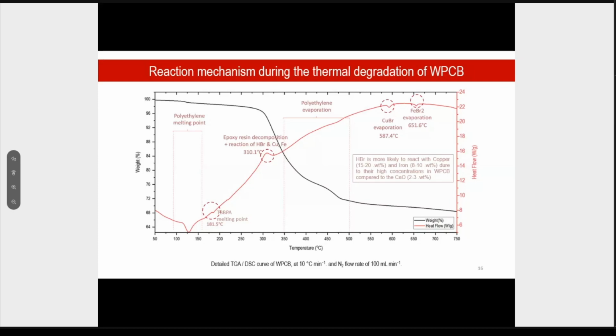Then two events take place: the decomposition of the epoxy resins, which is an exothermic reaction, and also the reaction between hydrogen bromide and copper and iron. Based on the concentrations of copper, iron, and calcium oxide, we can predict that this reaction, if it takes place, will take place mainly between hydrogen bromide and copper, followed by iron, considering their concentration, which is about 20% copper and 10% iron, while the calcium oxide is very low in concentration. Then it's followed by the evaporation of polyethylene, and two final small endothermic peaks related to the copper bromide and iron bromide evaporation at higher temperature.